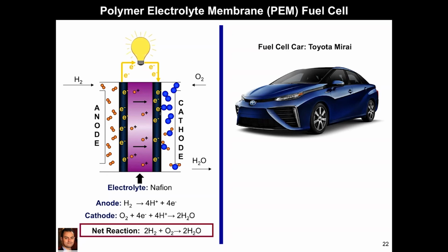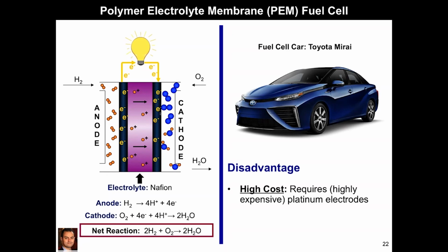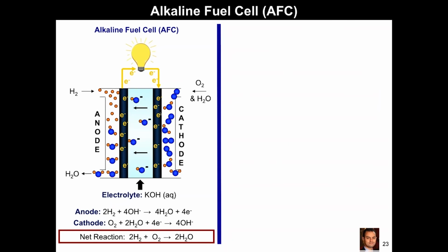And so people are very familiar with this. And one of the downsides is the high cost because the oxygen reduction kinetics is pretty sluggish and requires platinum electrodes. So one alternative that folks have looked into is the alkaline fuel cell. And the main difference here is instead of protons going from the anode to the cathode, we have hydroxide anions moving from the cathode to the anode. And typically in the past, people have used liquid electrolytes. So the advantage of using alkaline fuel cells is that the oxygen reduction kinetics are very different in basic environments, and you could use non-noble metal catalysts such as nickel, so that's a huge advantage.